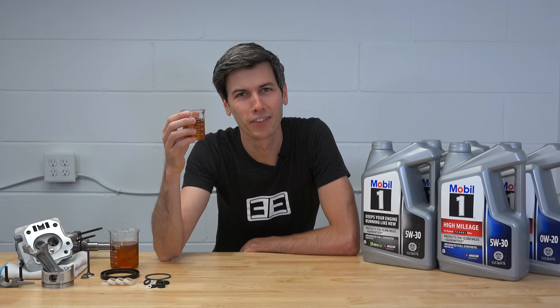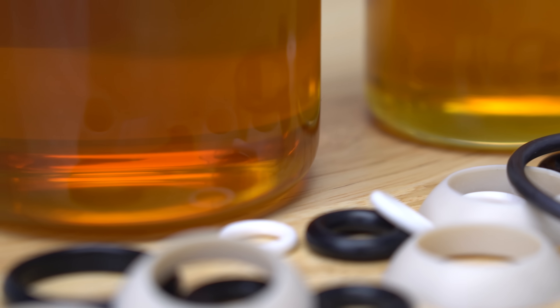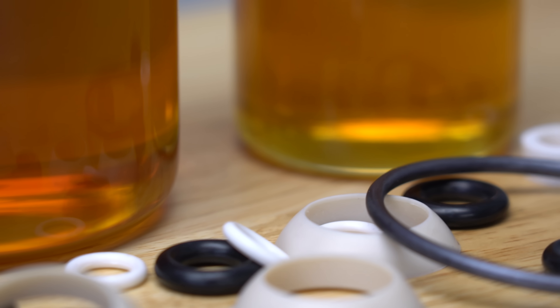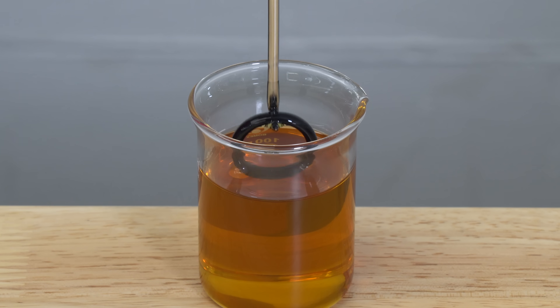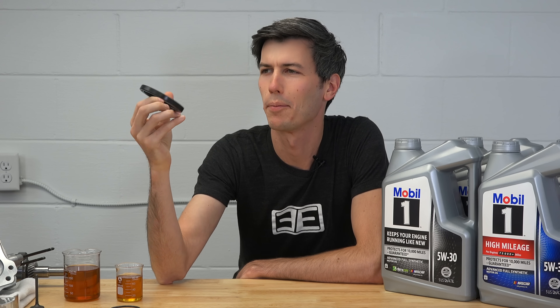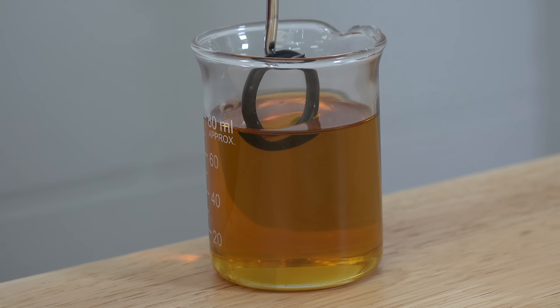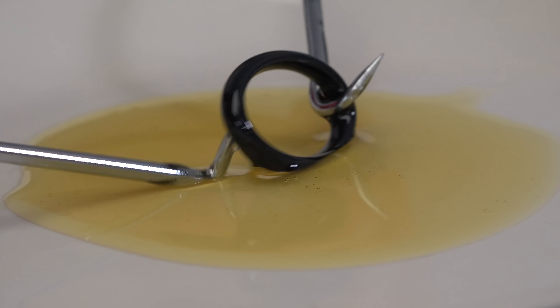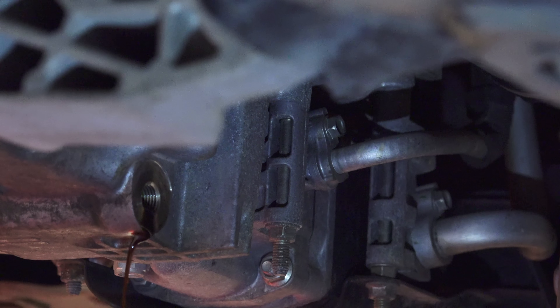Ultimately it comes from bad experiences in the past. Some of the early synthetic motor oils were ester based, and some engine seals are also ester based, so there's a compatibility issue there. Esters can cause swelling of engine seals, and a little bit can actually be a good thing. But if the ester concentration of the oil is too high, you could see excessive swelling of the seals, a drop in the seal's hardness, or a loss of tensile strength. You want the seal to maintain its properties regardless of what the engine is doing — hot or cold. With some early synthetic motor oils, likely with base stock formulations no longer used today, the oil wasn't compatible with the engine seals, so you found oil leaking all over your driveway.